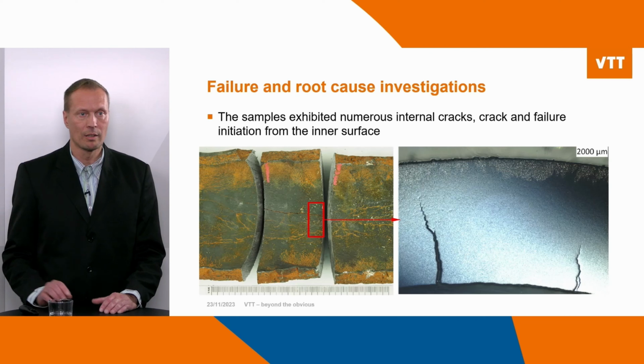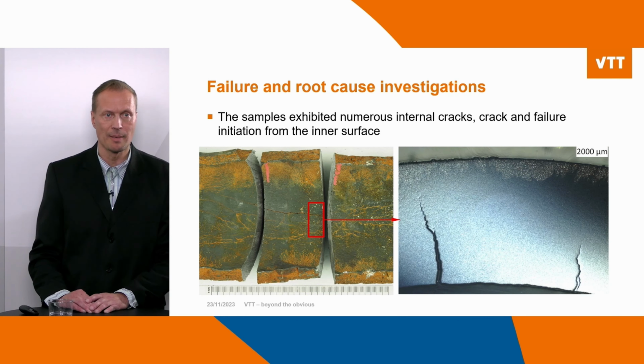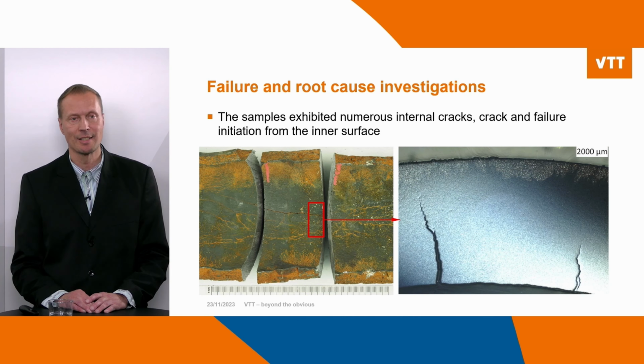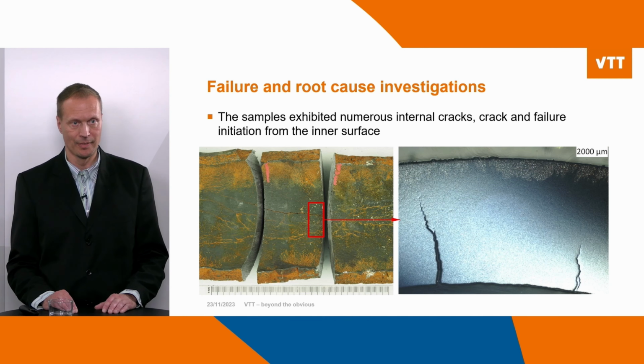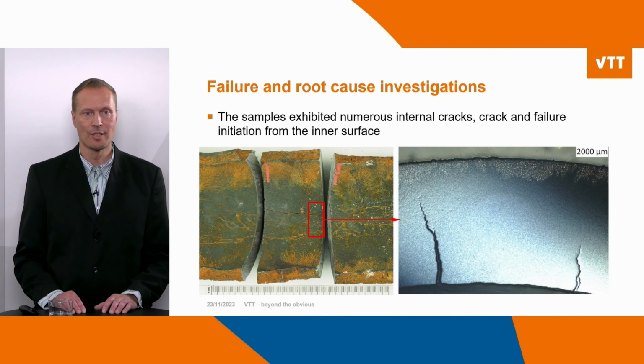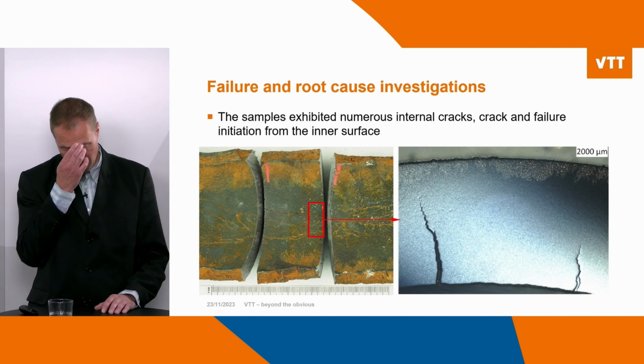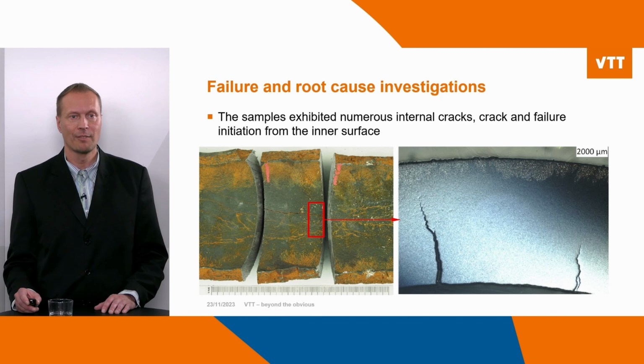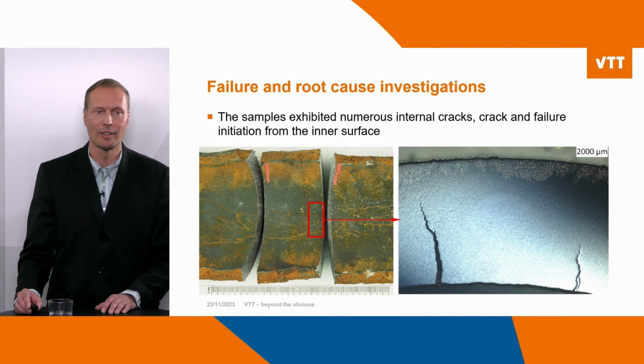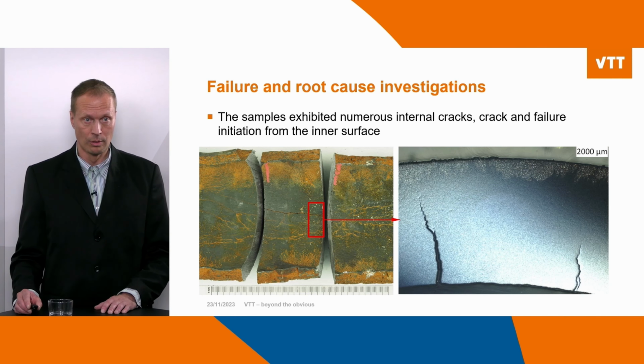Closer visual look revealed that these samples exhibited numerous internal cracks, and these cracks and failure initiated from the inner surface of the pipe going towards the outer surface of the pipe. And if we look at the right-hand side figure here, we can see two quite major cracks initiating from the inner surface going towards the outer surface of the pipe.